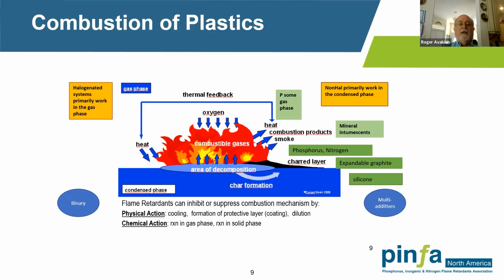The inorganic hydrates, like aluminum trihydrate or magnesium hydroxide, also work, basically, by going through an endothermic decomposition. They give off water, and at these temperatures steam, which typically tends to dilute the amount of oxygen that's available for combustion. And this endothermic reaction also takes in heat, so it tends to cool the area of combustion.